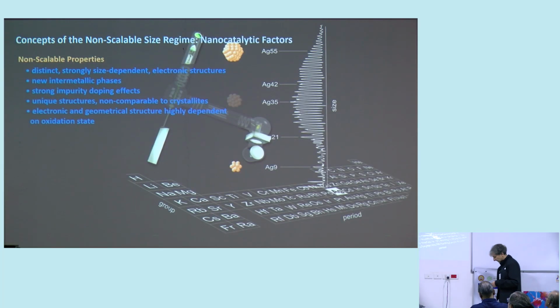So there are also some concepts that can guide us through catalysis with these small clusters. We have these distinct size-dependent electronic structures. We can also have new intermetallic phases, which do not exist in bulk materials. We have strong impurity effects. That means you can dope, for instance, a gold cluster with cesium, and you can charge the gold cluster. This changes the reactivity, for instance, for the oxidation of CO.